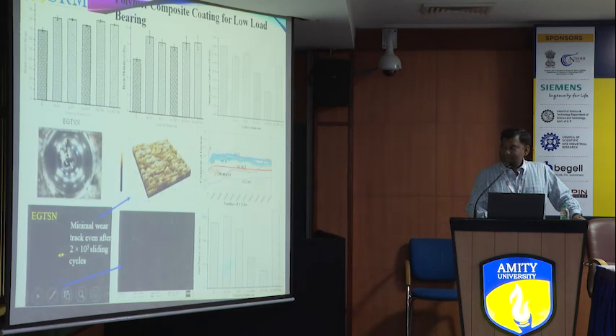With EGTSN, you can see here that nanotextures are formed. Due to the nanotextures, the surface is hydrophobic, and due to the hydrophobicity, adhesion is less, and it shows a low coefficient of friction. Wear is also very minimal. We can't observe it, and when we enlarge, there is a very smooth surface. It was tested at 2 Newton load. So these types of coatings are helpful for low load applications. For high load applications, there is still a research gap in this field, so you can think of how we can develop for high load also.